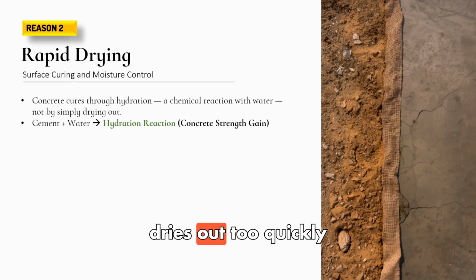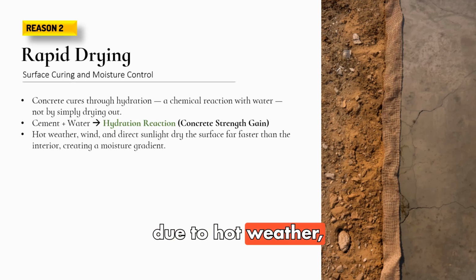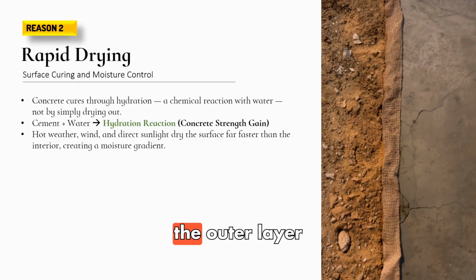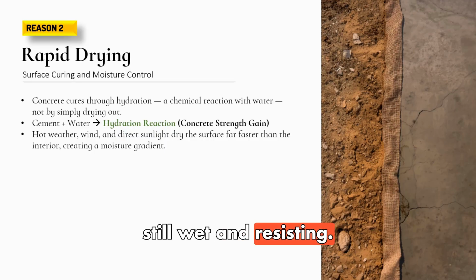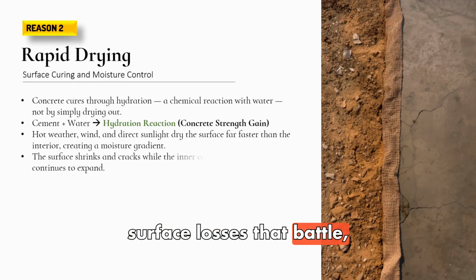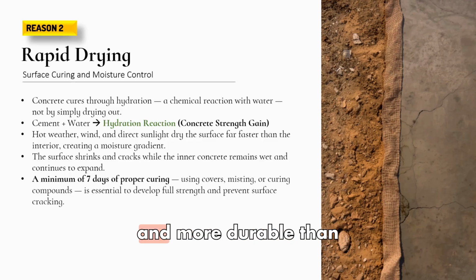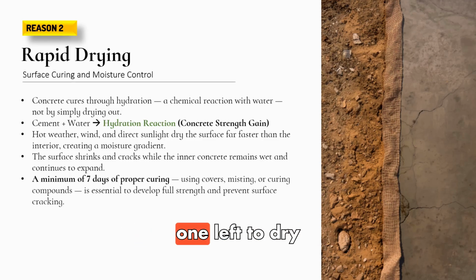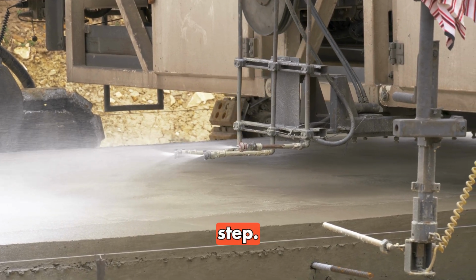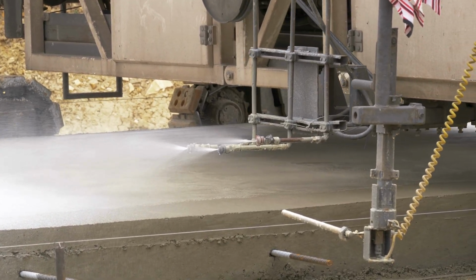If the surface dries out too quickly due to hot weather, wind, or direct sunlight, the outer layer wants to shrink while the inner layer is still wet and resisting. The surface loses that battle and it starts to crack. A slab that is properly cured for 7 days can be significantly stronger and more durable than one left to dry on its own. So curing is not an optional step, it is a structural step.